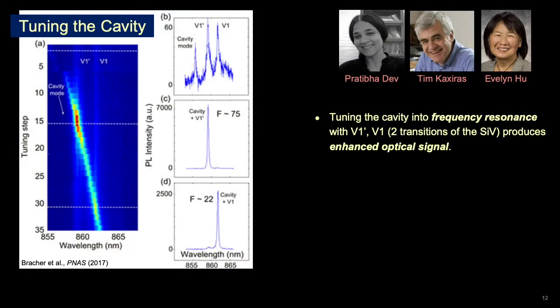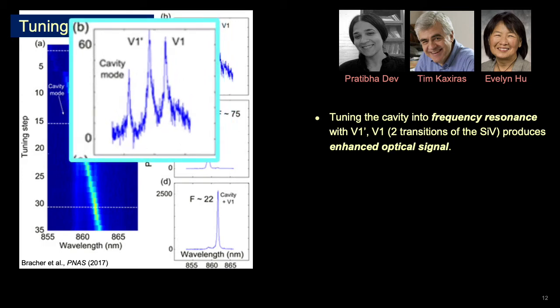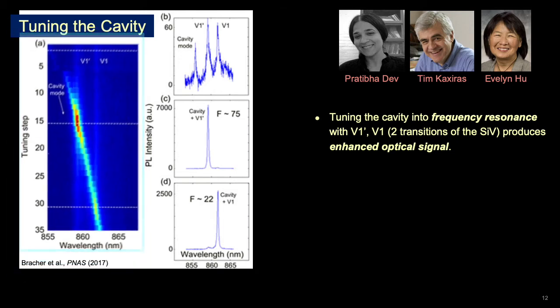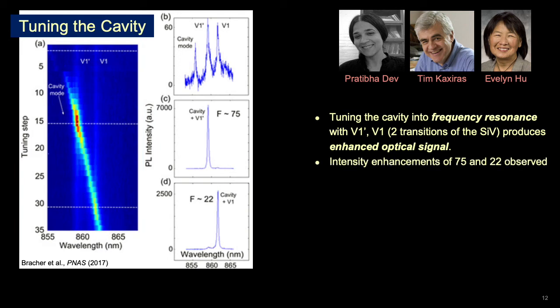When we tune the cavity frequency, beginning in a situation where this is the cavity mode — this is called V1, which actually has two incarnations because of one ground state and two different excited states, called V1 prime and V1. This shows a successive tuning where we just changed the natural frequency of the cavity mode. As we tune successively, we move this cavity mode into frequency resonance first with the V1 prime and then with the V1 signature. What you can see clearly is that on tuning into frequency resonance, we can enhance the output intensity of those transitions by factors of 75 and 22 respectively. The details of why we see different enhancement factors are quite interesting and actually tell us about the power of these cavities in understanding the local atomic environment of these defects.